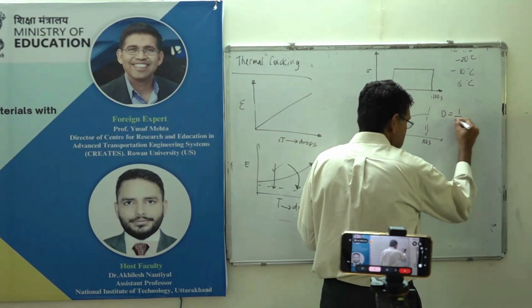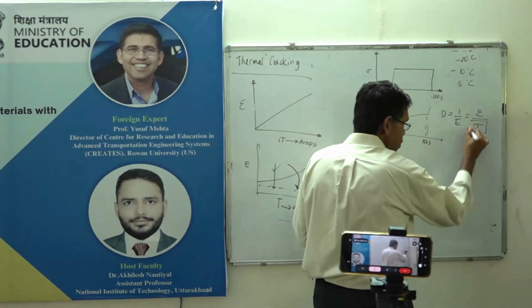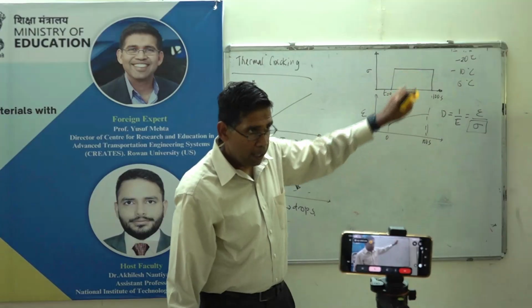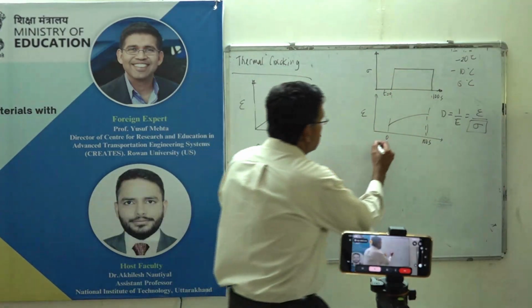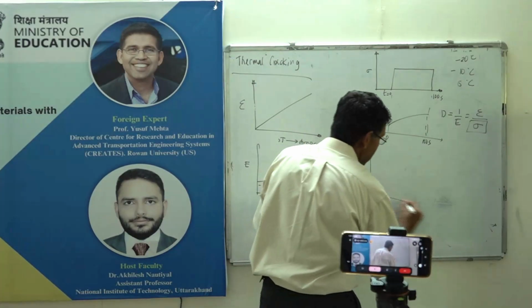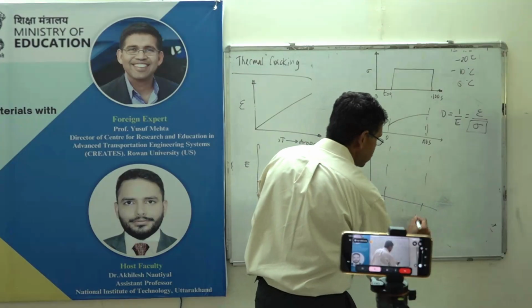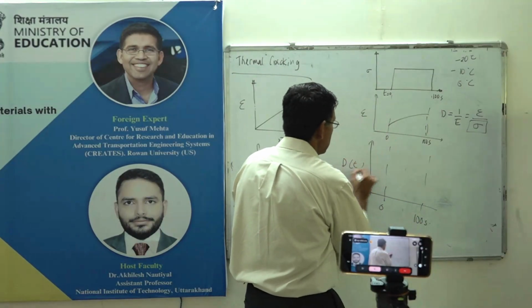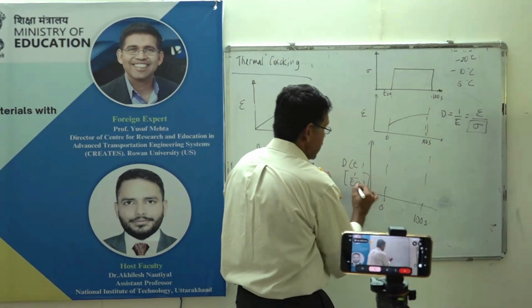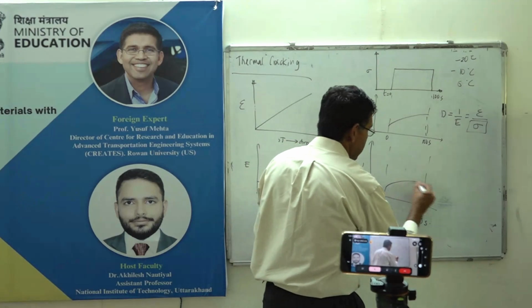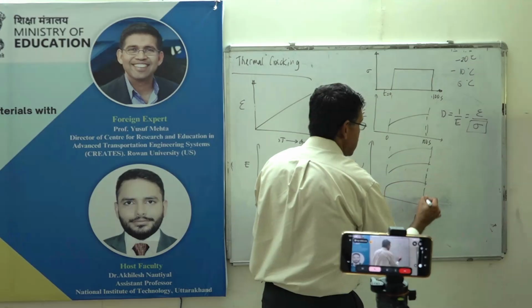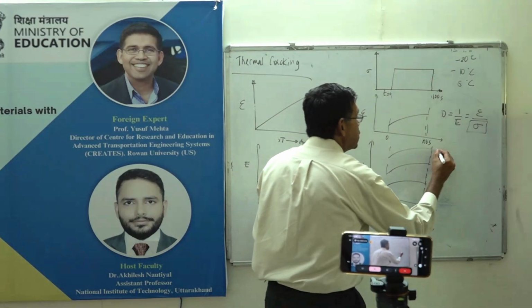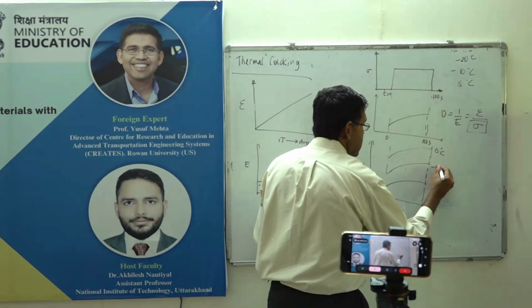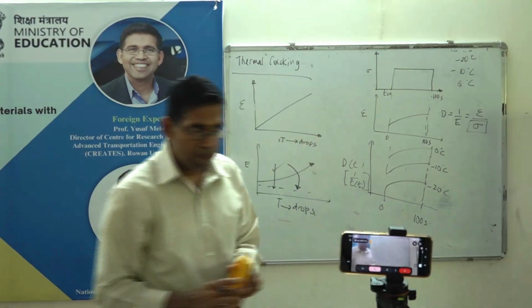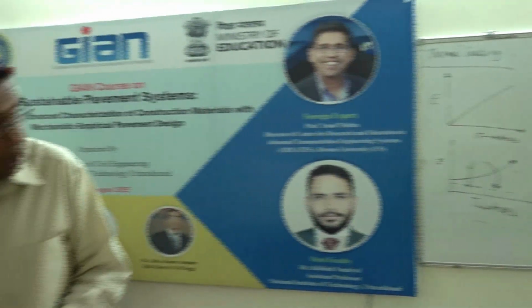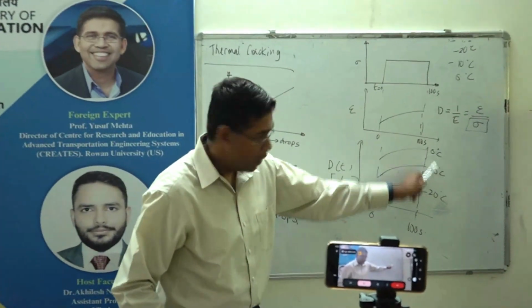D is 1 over E, which is epsilon over sigma, because sigma is constant. Sigma is constant, and epsilon is changing. So my compliance will increase with time, and now you do the same thing from 0 seconds to 100 seconds. Compliance D of t, which is 1 over E of t, if you don't know what exactly is inverse, and I will do this, inverse of stiffness. Okay, so this is 0 Celsius, minus 10 Celsius, minus 20 Celsius. So it is softest at 0, least soft at minus 20.